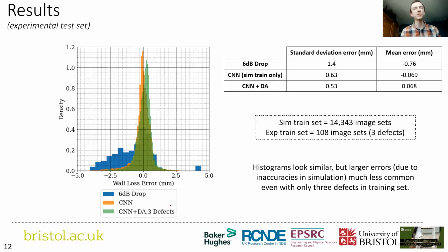And to show you the results of that, we've got the same histograms as before with the blue and the orange one. And with this new one, which only has data from 3 defects, the simulated training set is 14,343 image sets, but experimentally I've only got 108. And despite that being so small, while the histograms look quite similar, if you look at the extreme errors, they're massively reduced. We've only got a standard deviation of 0.53 now, which is a significant improvement, seeing as this is only from 3 defects.